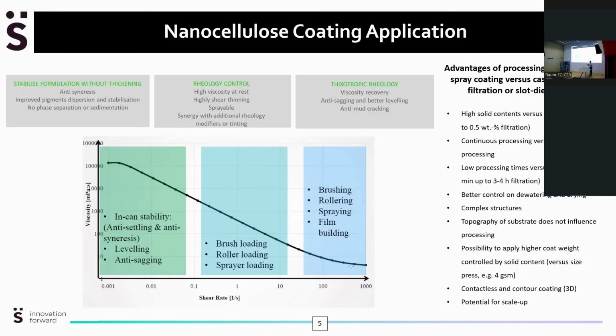And of course, if you also look into other substrates or 3D forms, spray coating becomes a technique that is necessary to use. And the intrinsic properties in order to be able to spray coat nanocellulose are the rheological characteristics, where you see indeed a strong decrease in viscosity as a function of the shear of the coating. This means if a high shear is applied on the coating, that we can get here low viscosity, which makes the nanocellulose spray coatable, mainly, for example, due to orientation of the fibrils under the pressure of the spray coating. Otherwise, if the tension is released, the nanocellulose can recover, it regains its viscosity, and it can dry into a solid film.